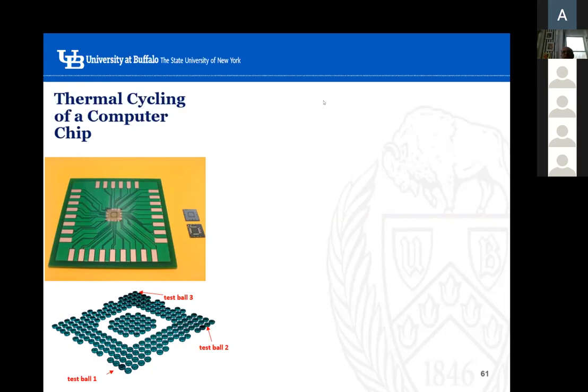Then basically one constant is related to half of the ductility. The A constant is nothing but the ductility of the material divided by 2, the first constant. And the second constant, the index N, depends on how much detail you have in deriving the cyclic hysteresis loops. According to that, the N number can change. Definitely it can change. But for the designer, they use some number like 0.5, 0.6 or something. So N is a fitting of the curve.